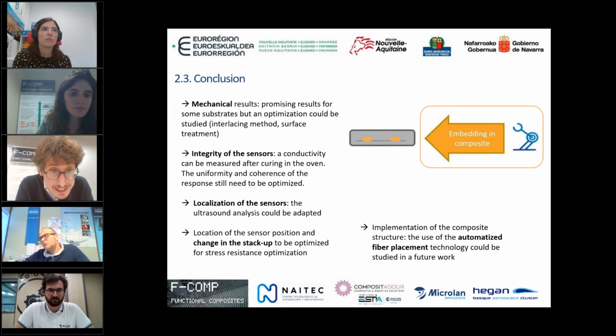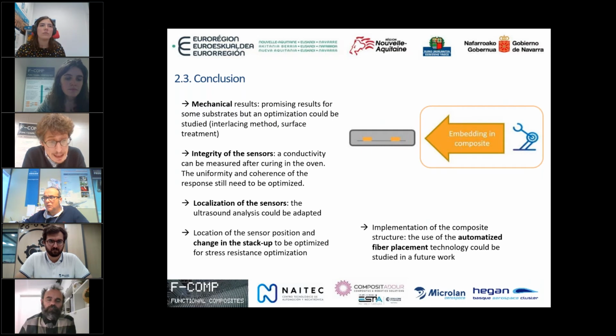The integrity of the sensor, as explained, is improved by getting a proper cure of the sensor before putting it in the oven with the composite. And for the location of the connections, it is needed to add probably some reference for having a better machining, and even using an automatized fiber placement will help to do that.